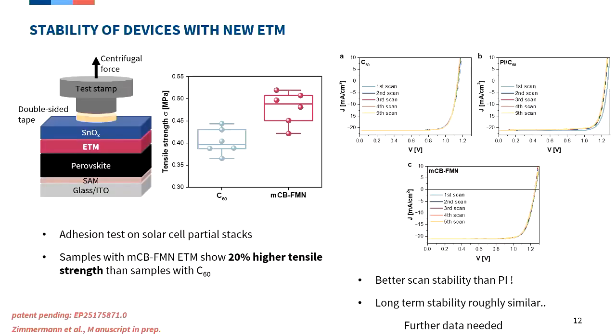In terms of scan stability - at least short-term stability, not long-term decade tracking outdoors - you see that typically you use what we call pyrazinium iodide interlayer to get the best efficiency, but there's a trade-off in consecutive scans that you don't have with the new molecule. So we're confident that higher stability is also given with the new molecule.